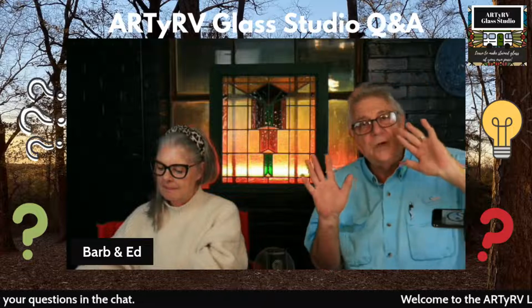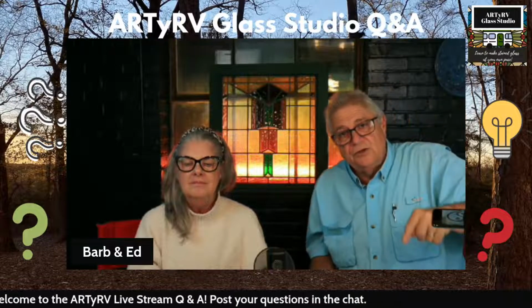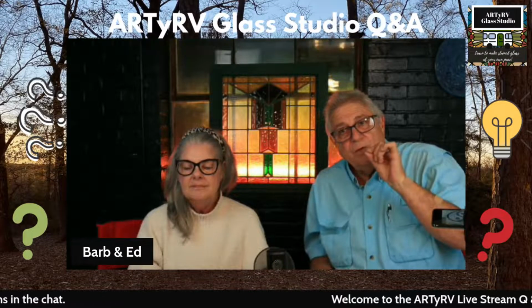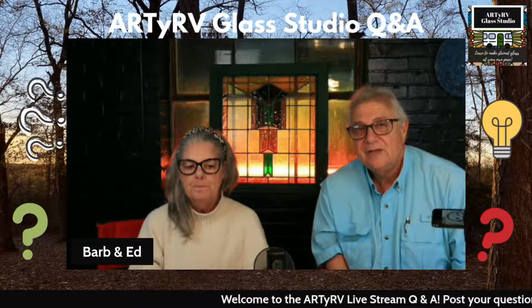So anyway, what we did is once we installed them, there's no silicone on the stained glass or the clear glass. Once we put the glass in behind the clear glass, we came back with our 1/2 by 1/2 pre-punch aluminum stop, and we drilled and countersunk. On the long pieces that were 34 inches, there were 3 screws in each stop, and on the bottom and the top, there were 2 screws in each stop. Then we just ran a small bead of clear silicone around that so that the windows aren't fixed. The air moves through them. And we haven't had one problem with those windows sweating, which is awesome. Right, right. So I hope that answers your question, Ray.